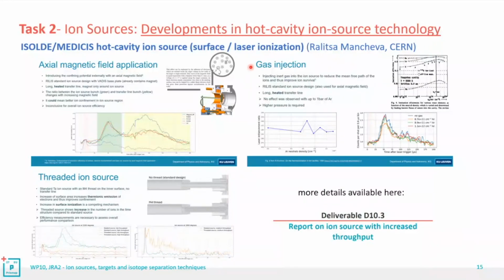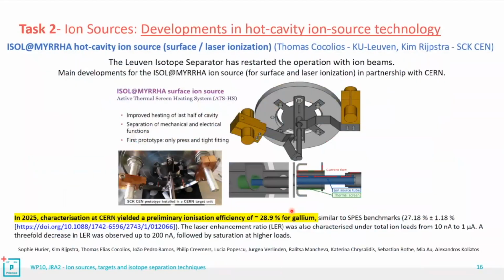Unfortunately, these 2 tests did not satisfy the expectations, but the third one registered some improvements for the laser ionization process. During this test, they threaded the internal surface of the hot cavity. In this way, they increased the surface area for thermionic emission of electrons, and it seems that this improved the ion confinement, so the performance of the source. These are preliminary results and need to be consolidated, but all details of these tests can be found in deliverable 10.3. Another important aspect for hot cavity ion sources is the temperature profile.